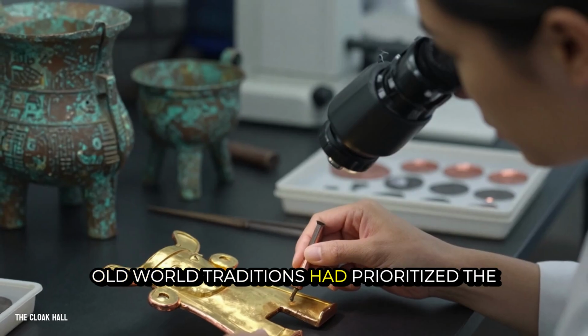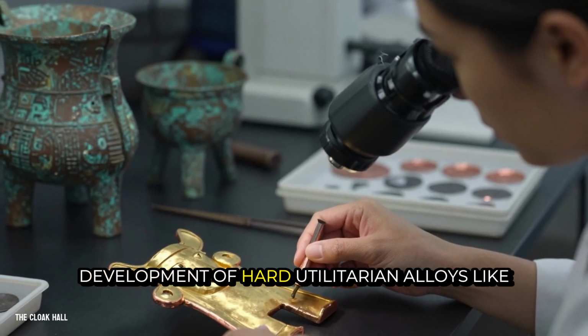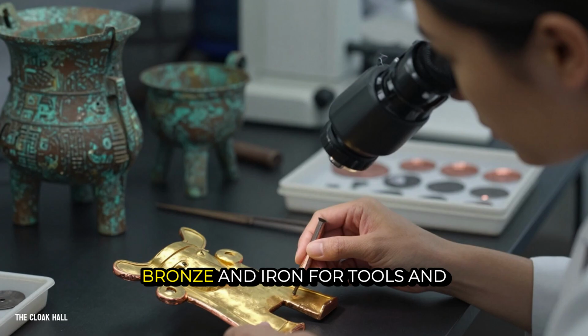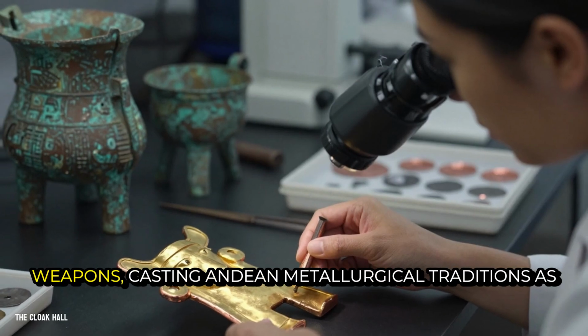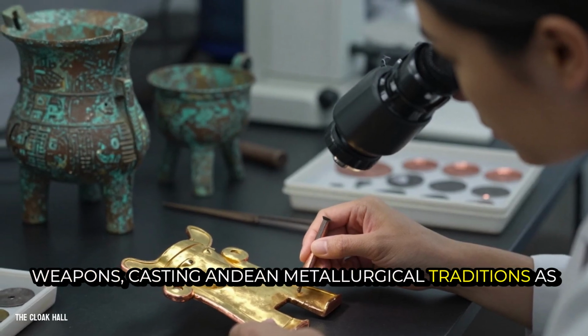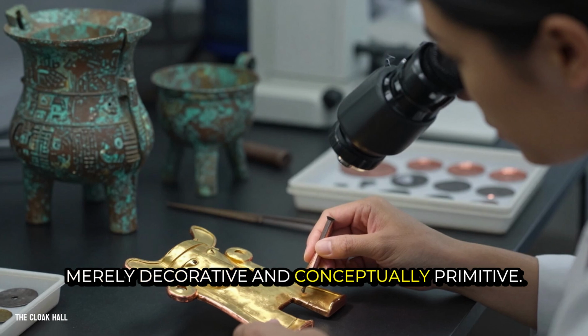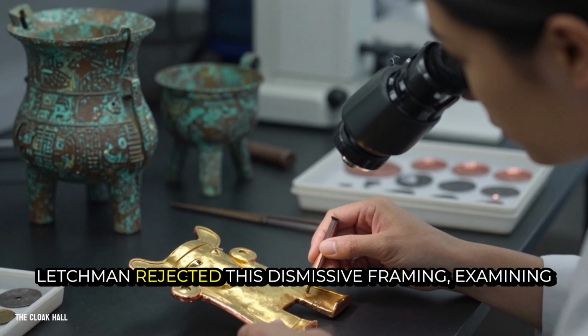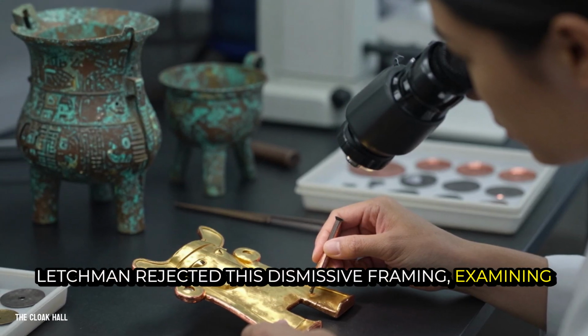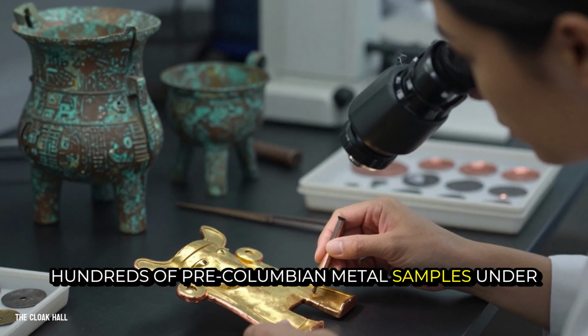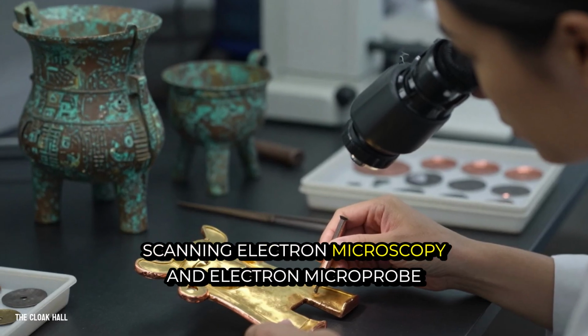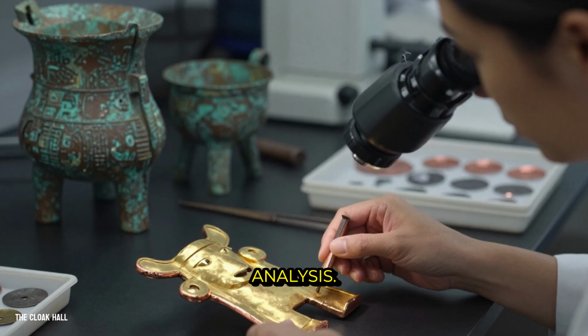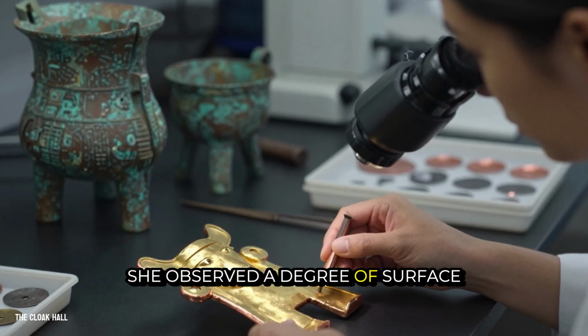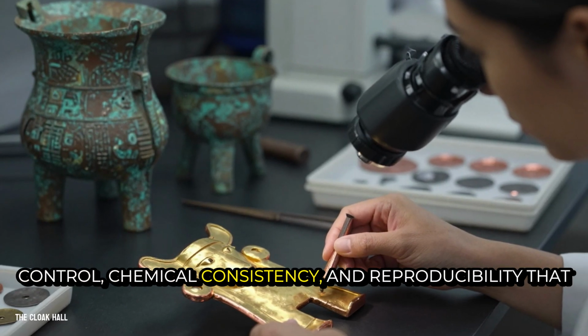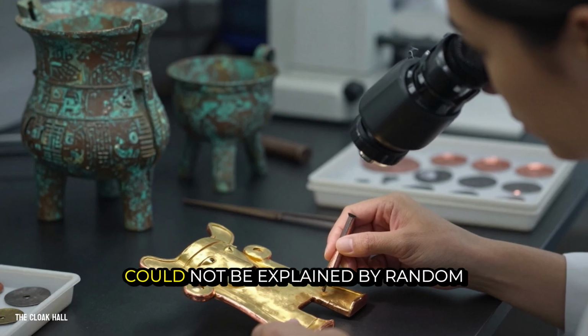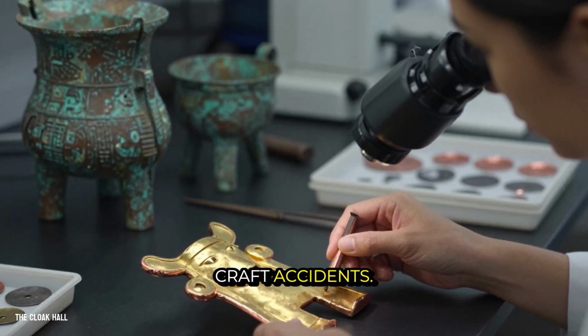Old World traditions had prioritized the development of hard, utilitarian alloys like bronze and iron for tools and weapons, casting Andean metallurgical traditions as merely decorative and conceptually primitive. Lechtman rejected this dismissive framing, examining hundreds of pre-Columbian metal samples under scanning electron microscopy and electron microprobe analysis. She observed a degree of surface control, chemical consistency, and reproducibility that could not be explained by random craft accidents.